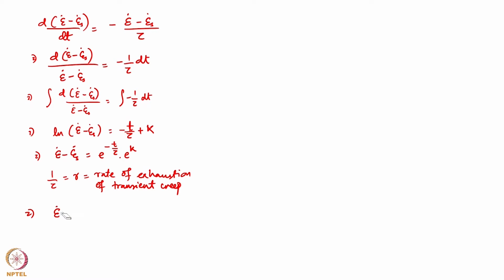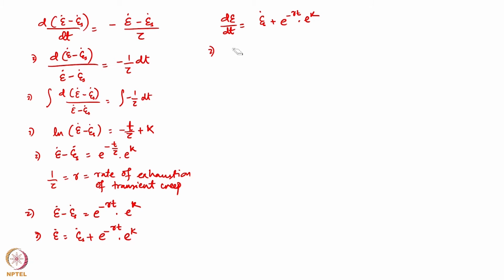So, this implies epsilon dot minus epsilon s dot is equal to e to the power minus r t into e to the power k. So, epsilon dot is equal to epsilon s dot plus e to the power minus r t into e to the power k. So, d epsilon by dt is equal to this, which implies integration of d epsilon is equal to integration of epsilon s dot plus e to the power minus r t into e to the power k dt. At time t equal to 0, we get the instantaneous strain epsilon naught.